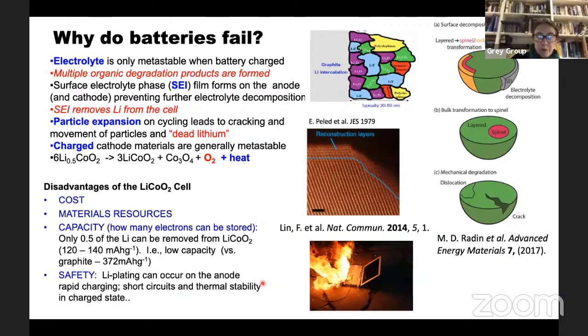So I just thought I'd spend a few minutes and discuss, why do batteries fail? They do that for a number of different reasons, but they have some of the same sorts of origins. And one of them is an organic chemistry problem. And that's simply that you have an electrolyte, and yet you're asking this electrolyte to operate at very low potential, so down close to lithium metal. And there is no electrolyte that is stable there, no organic material. And of course, water is definitely not stable at those sorts of voltages. Everybody knows that if you plonk a bit of lithium or sodium into water, you generate hydrogen very quickly.